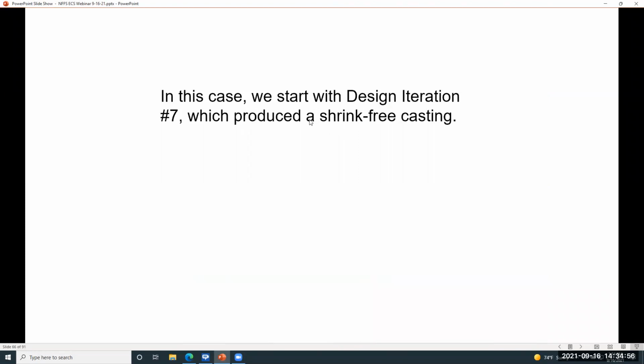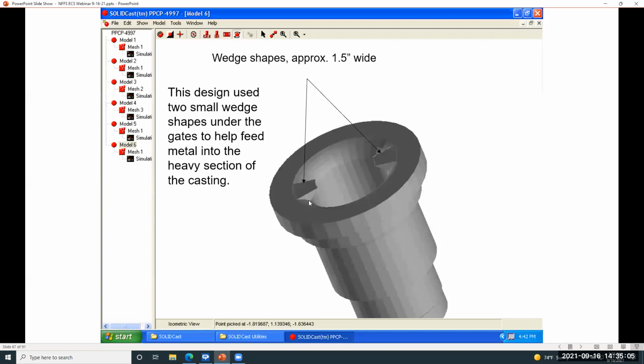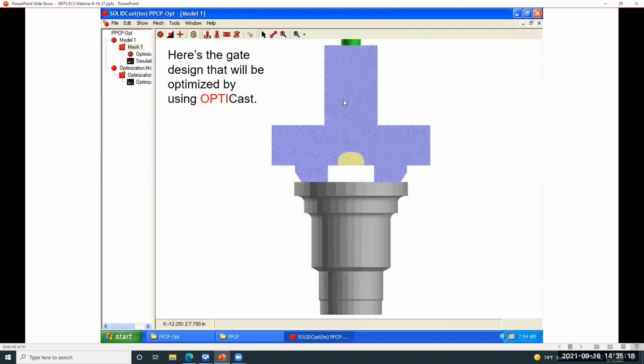Initial simulation was done to make adjustments trying to move that shrinkage out into the gating system. And that was actually done by putting a little wedge underneath the gate to open up the area through there. So this became our starting point, and then we added the current gating system into the model so that we can do an optimization. And we can see a couple of things here. We have the casting geometry, the gating system in blue, and fill material at the top in the green. So we're doing a filling simulation with this as well.